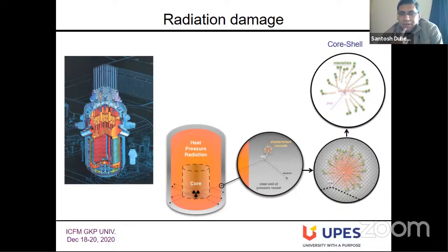We'll have non-equilibrium concentration of such defects. So we have these kind of damaged regions all over the material. So the fate of the material, what will happen to it after all these interactions with the energetic particle? The material will be highly damaged at the macroscopic level. Highly damaged means you have lots of defects, vacancies, interstitials, and clusters of these defects.